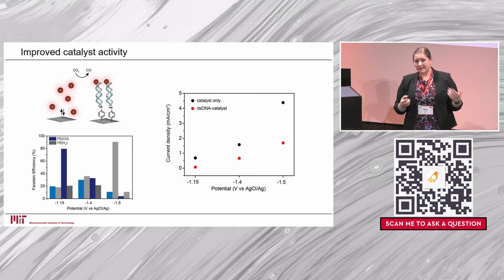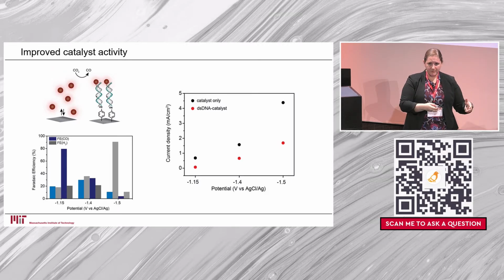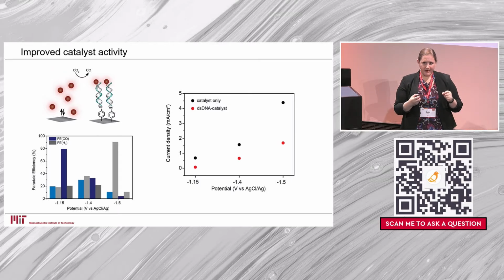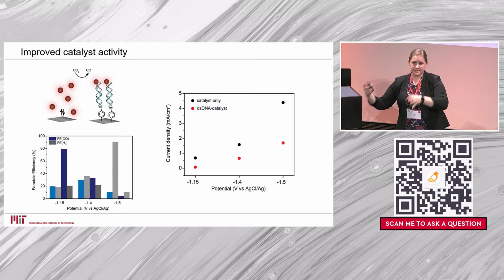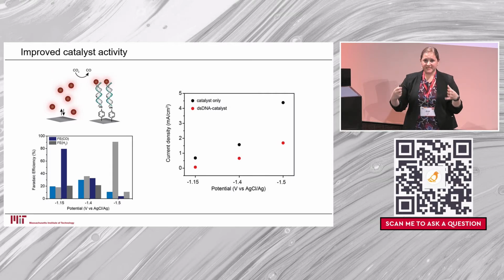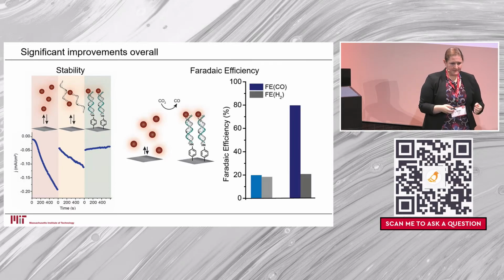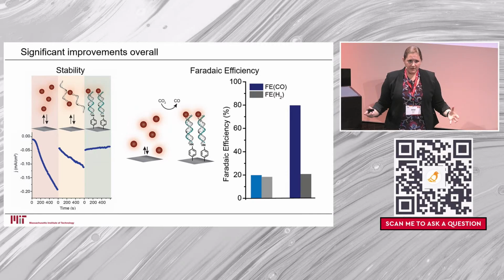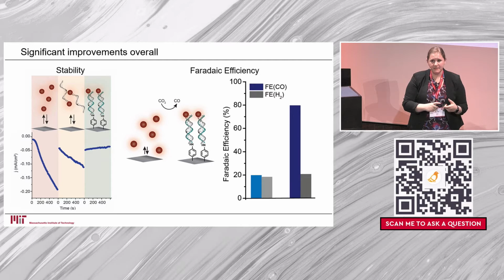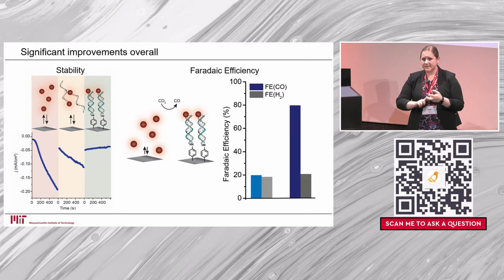I should also note that you can chemically synthesize DNA for about 1 cent per base right now. And we're using picomoles per centimeter squared of catalyst versus micromolar to millimolar in solution. So we're adding negligible costs while also decreasing the amount of catalyst we need by 10,000-fold. And so what we can see overall is that DNA allows us to not only significantly improve our stability, but also the amount of energy and the efficiency of how much energy it takes to convert carbon dioxide to carbon monoxide.